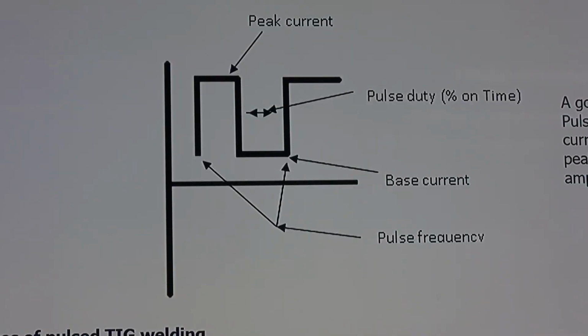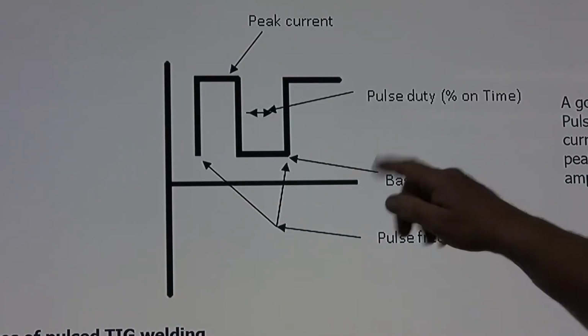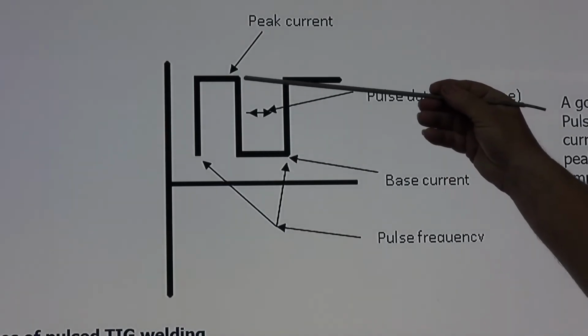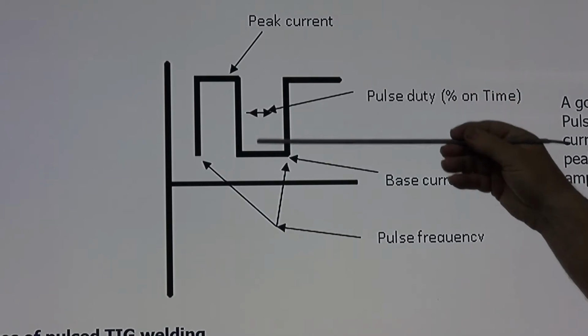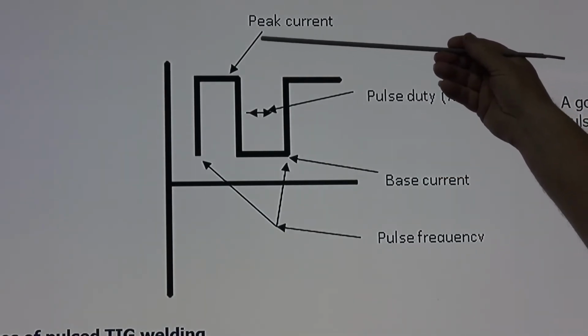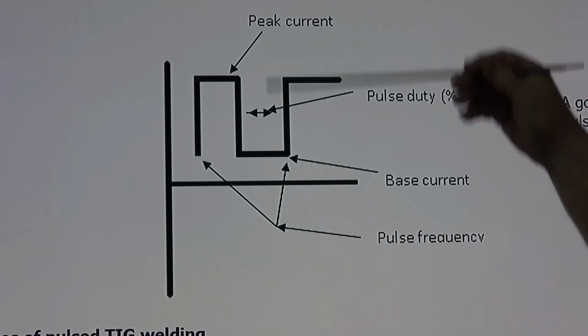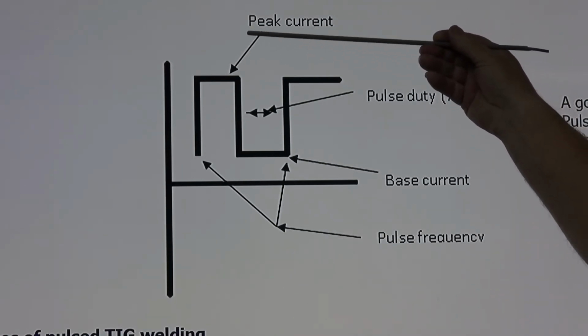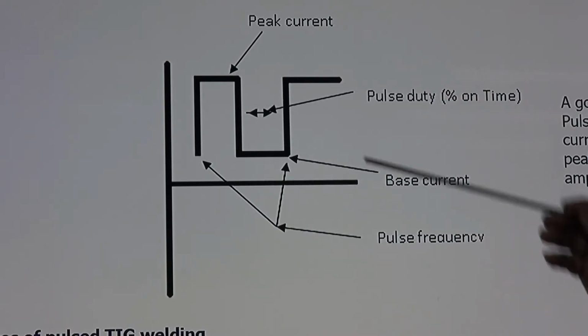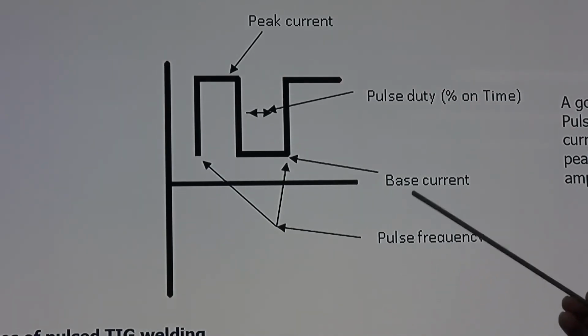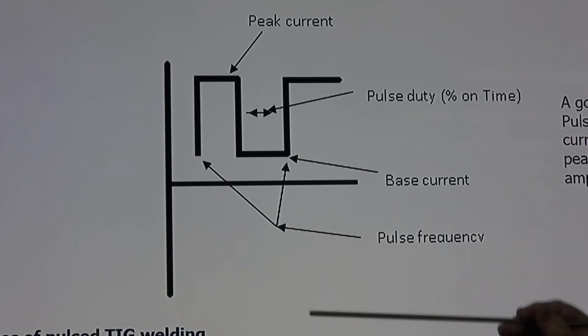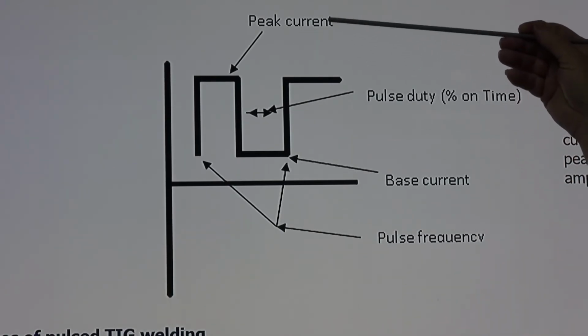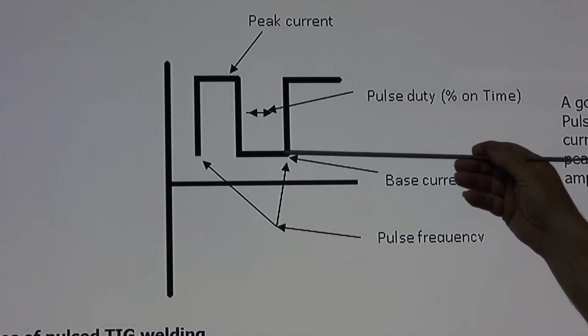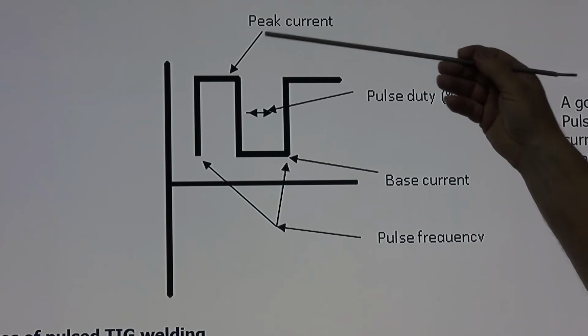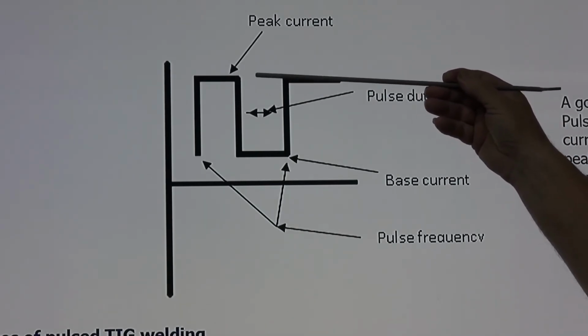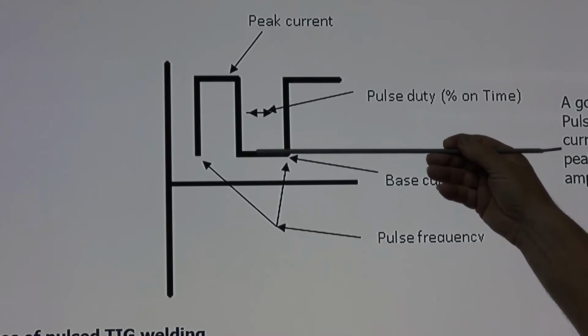We're going to talk a bit about pulse welding. Pulse welding is where we take a peak current and a base current and we switch between them. Peak current, base current, peak current, base current. The peak current we can set on the machine itself. An example would be we'll set the peak current at 100 amps. Then we've got to select a base current. A good base current is always about 40% of the peak current. So in my example, we have a peak current of 100 amps and we'll set the base current at 40 amps. So now we can put a bit of heat into the plate, get it really going, and then allow it to cool down and freeze.